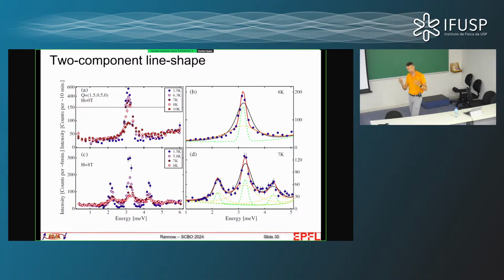You remember I told you that if I have a very sharp, well-defined oscillation frequency, then in my spectrum I should see a sharp peak. If this oscillation has a finite lifetime, in other words, if I excite a triplet and this triplet has a finite lifetime before it decays back again, then I would expect to see a Lorentzian line shape here, so a broadening.